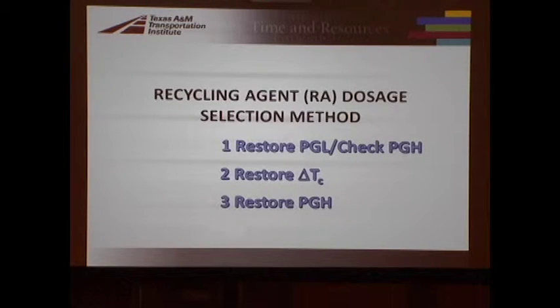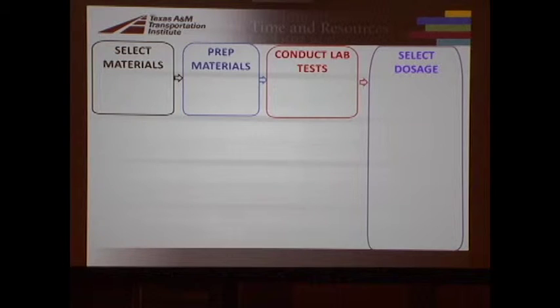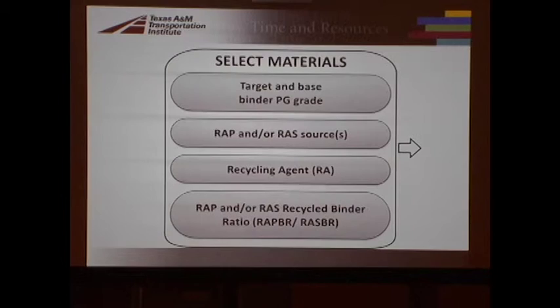So we came up with a preliminary recycling agent dosage selection method, this trial number 1. The first approach we came up with in phase 2, and then in phase 2B, which I'm going to describe in just a minute, with some more materials, we came up with these second 2 approaches, and we think we finally nailed it down. So I think this is hopefully of interest. So the first one, actually all 3 of them have these steps: select the materials, prep the materials, conduct the laboratory tests, and then those 3 different approaches differ in how we actually select the dosage.